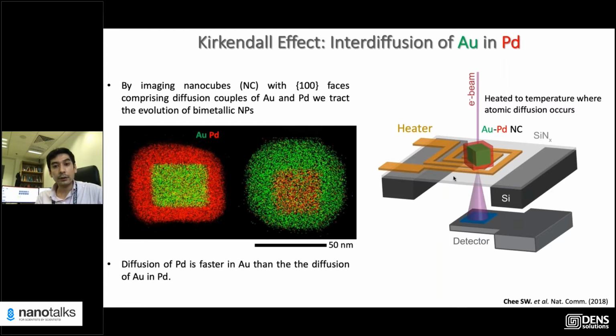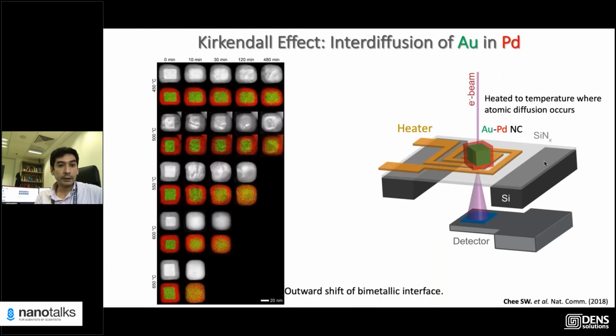Any of you who use a Wildfire are probably familiar with that, right? You put a particle on their commercial chip, and we just heat it, and then we monitor what happens. We do this experiment at different temperatures and see how the diffusion happens. At a low temperature, diffusion is quite slow. As the temperature goes up, you start seeing noticeable diffusion, and at this 650, it always intermixes, forming an alloy, right?